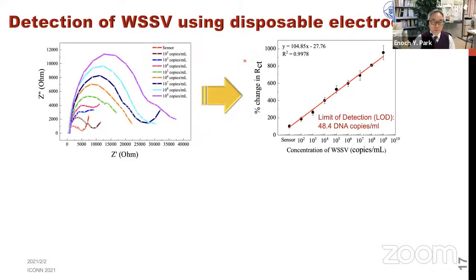And here, we have to confirm the linearity of this virus detection system. We provided 100 copy number per milliliter to 1 billion copy number per milliliter. It's shown here. This impedance value increased depending on the copy number of this WSSV. Based on this result, we make a calibration curve here. Very good calibration curve, with a correlation coefficient of 0.999. And using this calibration curve, we calculate the limit of detection, almost 48.4 DNA copy number per milliliter.